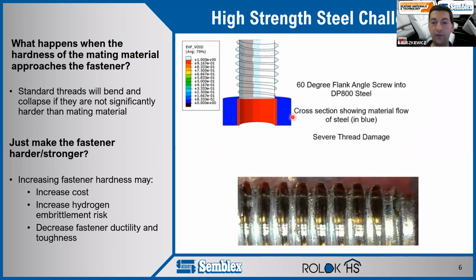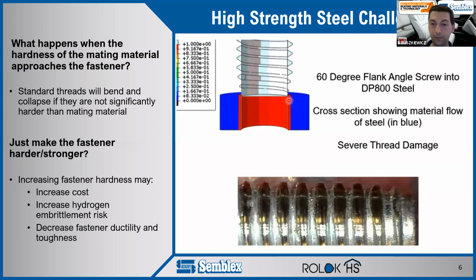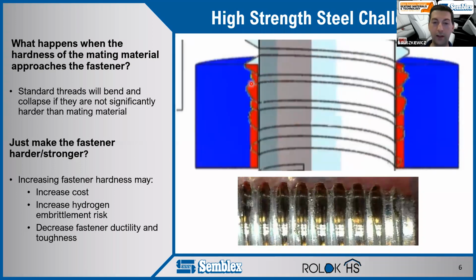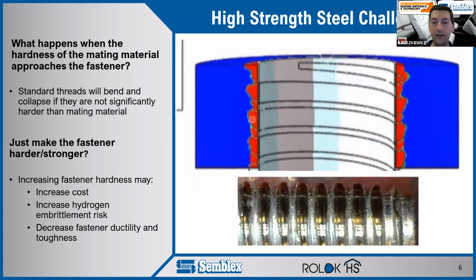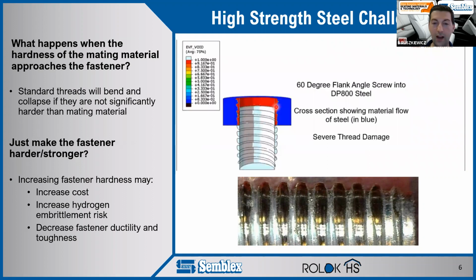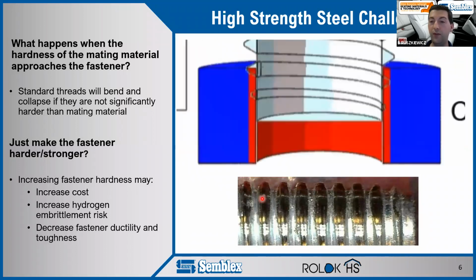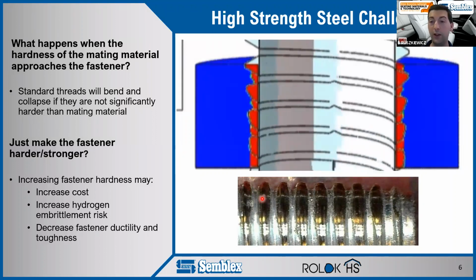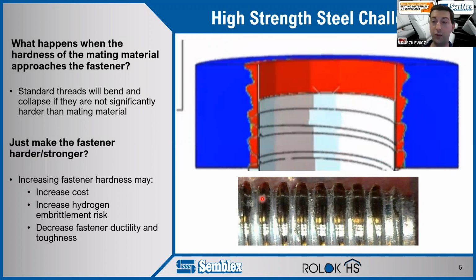So in this video that I'm going to play to the right, we have a 60-degree conventional thread rolling screw. It's an equivalent class 10.9, which means it has a tensile strength of about 1,000 megapascals. It's going to go into this blue material here, which is DP800 steel, which has a tensile strength of 800 megapascals. Now, when this screw tries to form threads in this material, you can see the threads, they bend and then they collapse. And this female thread that's left behind is not very well formed, but if you look at this screw, it looks a lot like this picture at the bottom, which is similar to the one we showed earlier, where when those threads fail, they bend and then they collapse down, and it almost looks like you just took the tops of the threads off. What you actually did is you just bent it and collapsed it.